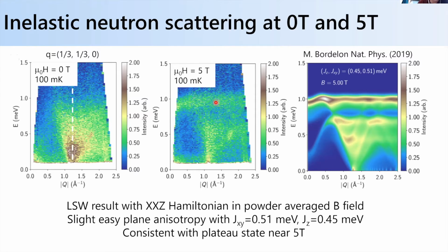And they can also utilize this subtle downturn here in this upper band to try and constrain what the deviation from Heisenberg exchange should be. And what they find is it has a slight XY anisotropy. So the XY exchange is 0.5 millivolt, and then JZ is about 0.45 meV. Okay, so we can get some sharper information.